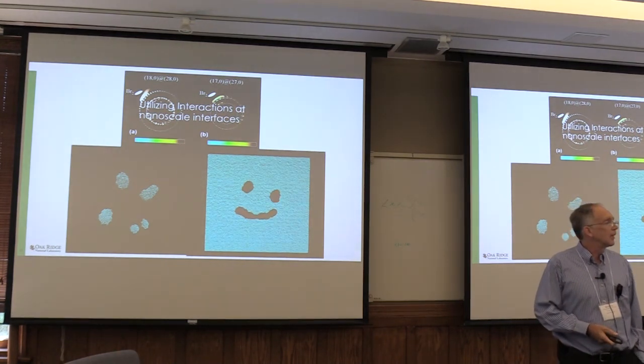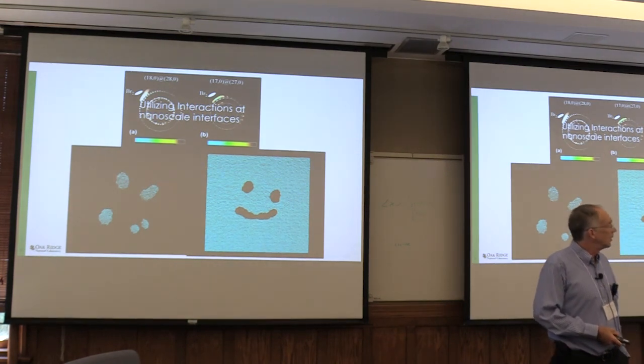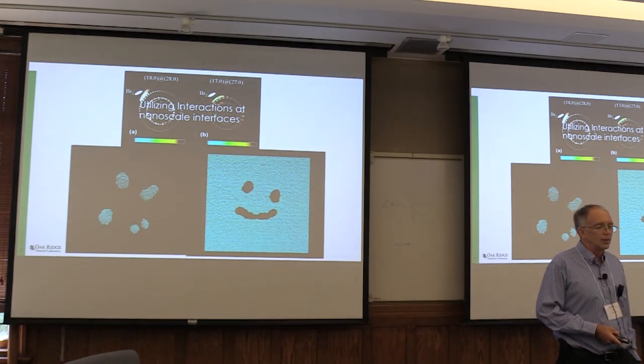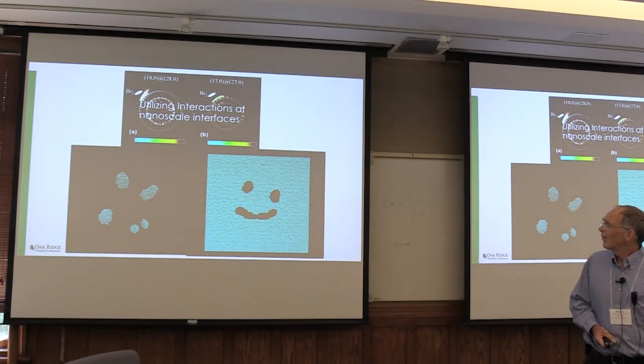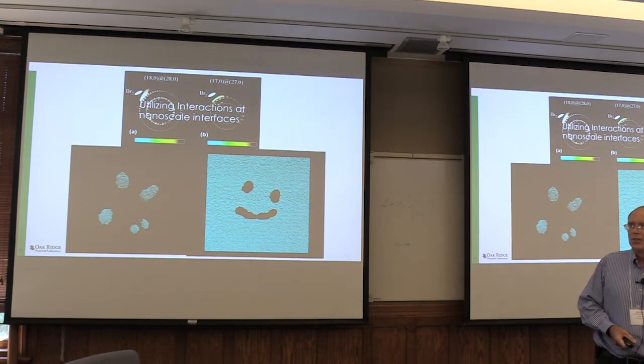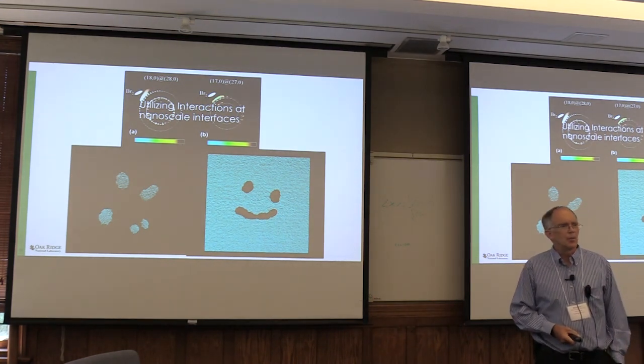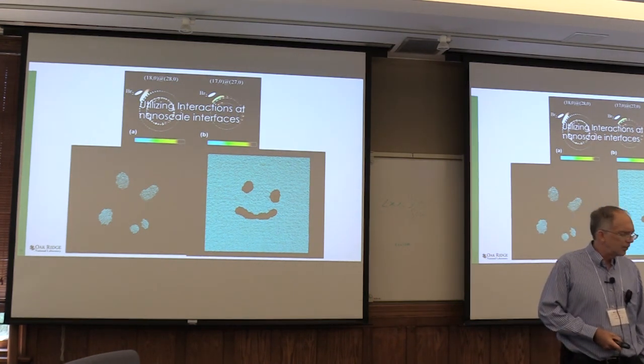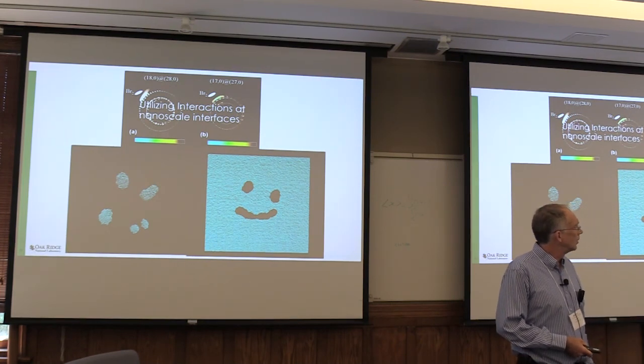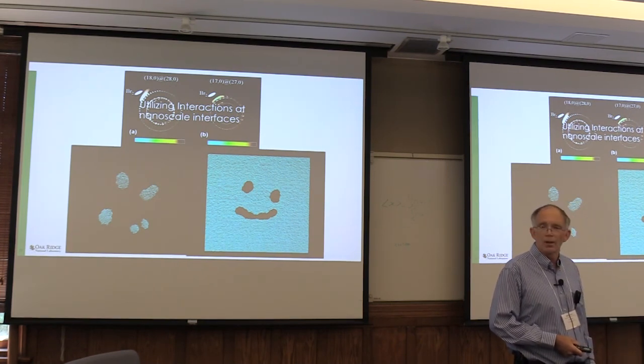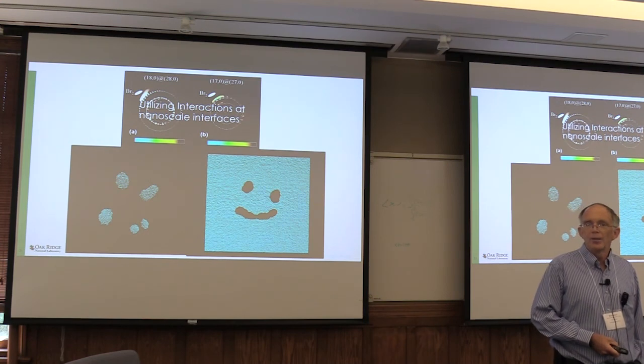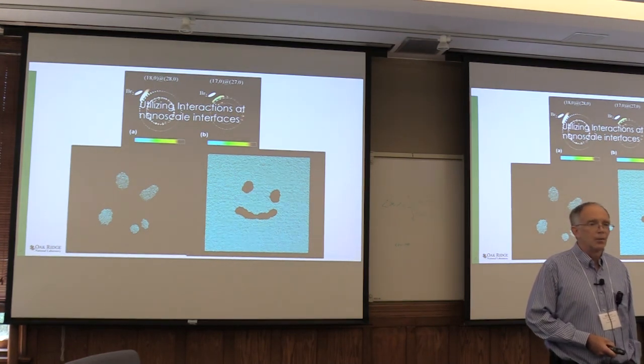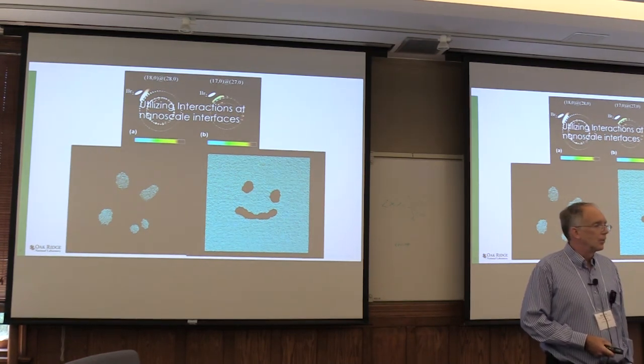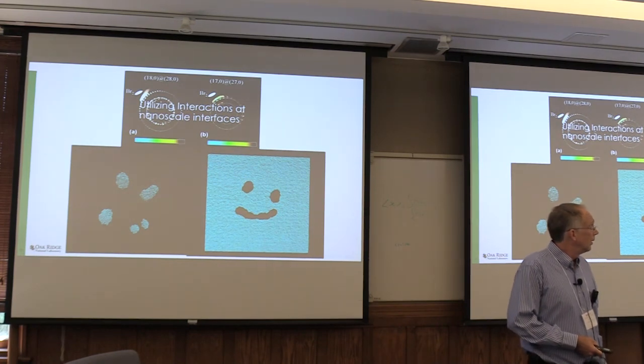And we can control it to make any structures we want by changing the interface and the interactions of the interface. Again, this is actually a reactive potential, an embedded atom model. And we found that there are some funny things you can do with this sort of stuff. You can make super hydrophobic materials by structuring the interfaces so that no water can get on it, or no ice. Useful. Turns out, if you have a boat, it's pretty cool. If the surface of the boat is super hydrophobic, it can move pretty fast.